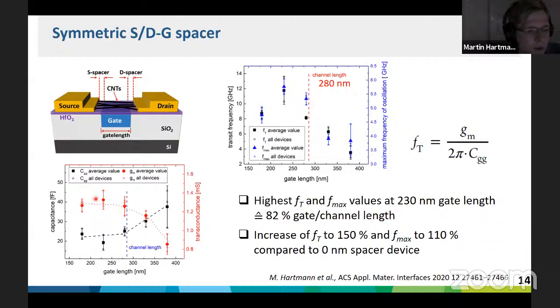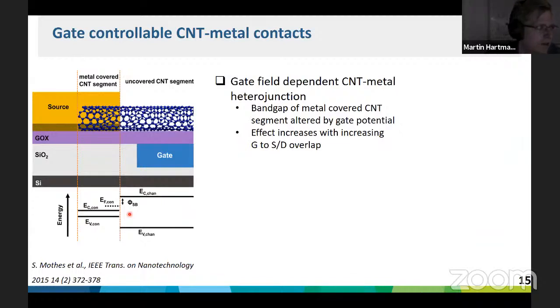But the gm trend was not as expected. We expected that when you bring the gate closer to the source and drain electrodes, you get better control over the barriers, and the gm keeps increasing. However, the trend was true for the first points, but then when you come closer to the channel length, the transconductance decreased, and that really surprised me. It took us quite a while to think about that, and the real origin is still under debate, but we have two possible explanations.